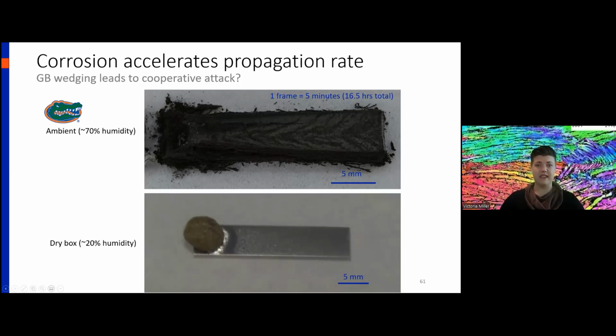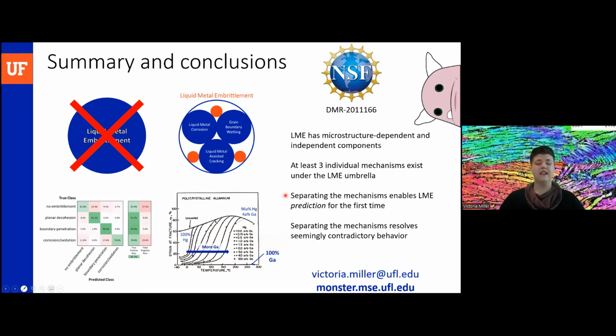So that's where I'll leave things. Hopefully what I've convinced you of is that liquid metal embrittlement has microstructure dependent and microstructure independent components. At least 3 individual mechanisms exist under the liquid metal embrittlement umbrella. And separating these mechanisms is the first step in actually predicting liquid metal embrittlement for the first time, because separating the mechanisms starts to resolve some of this seemingly contradictory behavior.